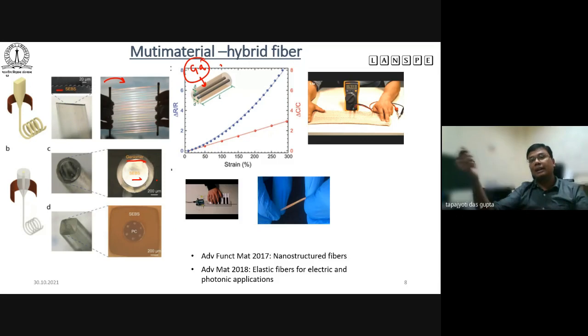And now you think about stretching it, right? So when you stretch it, if you have a single channel, let's say, the electrode will change in its length, because you are stretching, and similarly decrease in its thickness because your volume remains the same. And so the effective resistance changes because R equals rho L by A. Length is increasing, area is decreasing, the area being the width multiplied by the thickness. And this could be easily used as a strain sensor.